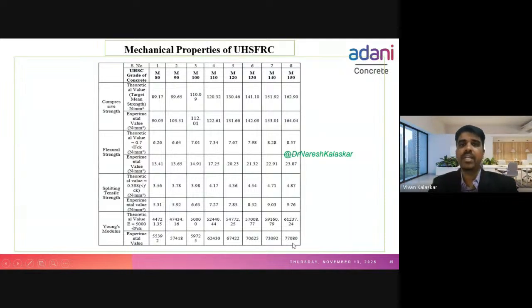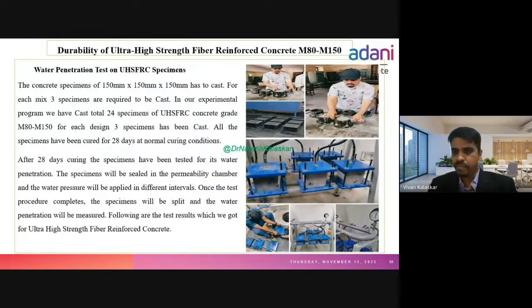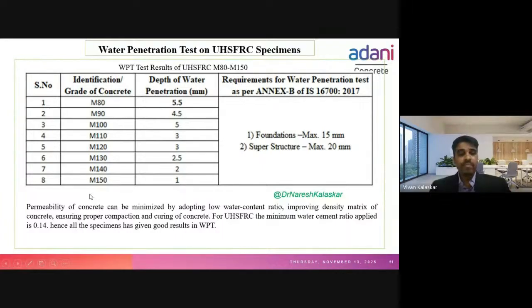So these are the exceptional properties of ultra high performance concrete made with Indian materials, with low cost materials. Now the durability tests. I have performed durability tests like the water penetration test and the chloride ion penetration test on UHPC specimens, and you will be surprised after seeing the results. M150 has water penetration of 1 mm. If you see the code IS 16700:2017, for foundations the maximum water penetration should not be more than 15 mm, and for superstructures not more than 20 mm. For M150, we got 1 mm water penetration.